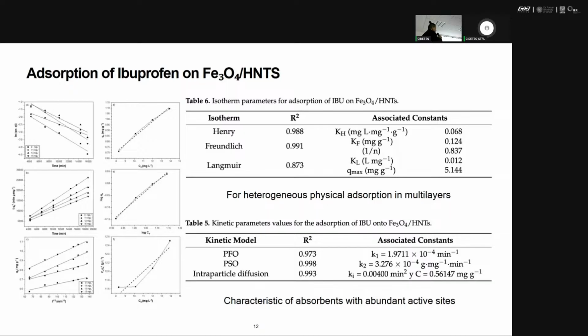And once I found the optimal condition, I made some models for the absorption kinetics. In this experiment I used the Freundlich isotherm and the pseudo-second-order kinetic model. This is characteristic of heterogeneous physical absorption in multilayers, and this is characteristic of absorbents with abundant active sites. It is useful because it could provide information about the pathway of the absorption.